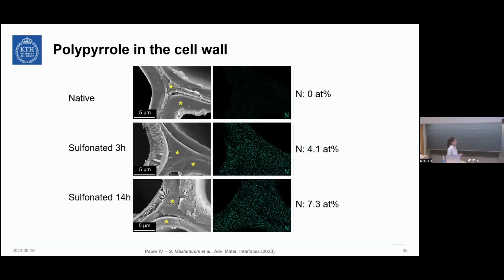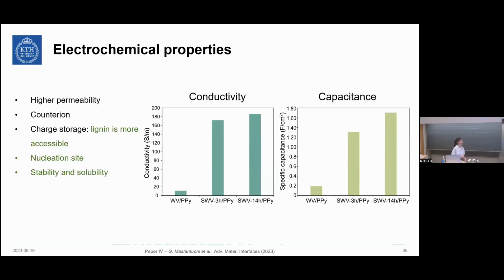The question remains if, however, we infiltrated the cell wall, which we're trying to achieve. And the answer is yes. And we could see this with the EDX. We mapped nitrogen, as nitrogen is present in polypyrrole, but not in wood. And we can see that there is an increase of the atomic percent of nitrogen the more we push sulfonation. And we could also see a uniform distribution of nitrogen both in the middle lamella region as well as throughout the cell wall. How does this, however, affect the electrochemical properties?